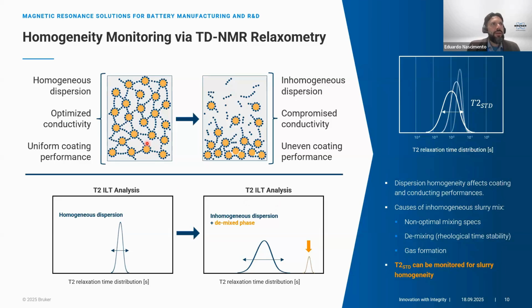So here you see the basic principle: when you have a homogeneous dispersion, this is where we have our optimized conductivity for uniform coating performance. When we do this TD-NMR analysis, more specifically the relaxation time analysis, and apply a fitting algorithm to that, you are going to see a sharp peak, which represents the average relaxation time for this sample. And the principle is that as we move toward an inhomogeneous dispersion, this peak is going to get broader and broader.